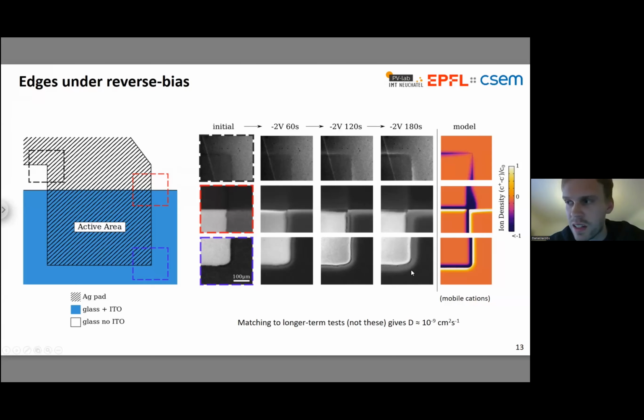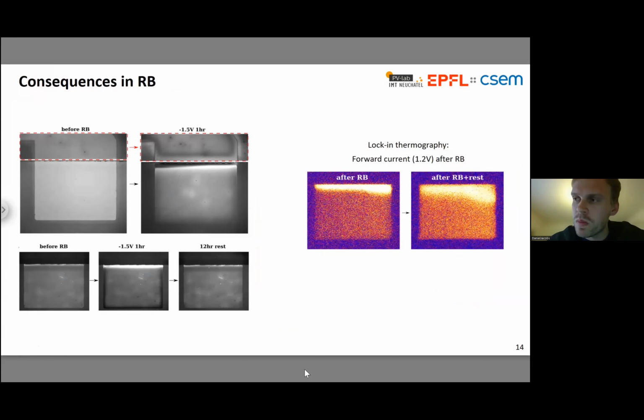And you can also use this data to get a bit of quantitative information, in particular by matching to longer-term tests, not the ones that I'm showing here. You can get estimates of the diffusion constant of our species. And in this particular test, I get numbers of about 10 to the -9 centimeters squared per second. Okay, so much for the verification. What are the consequences?